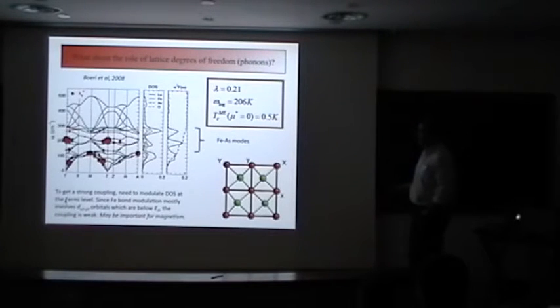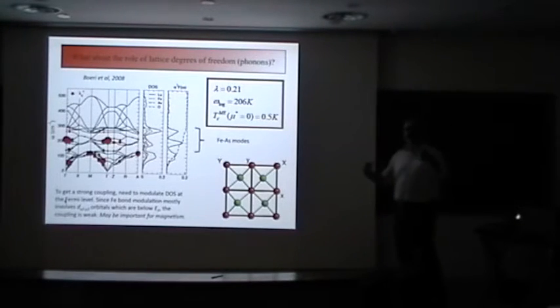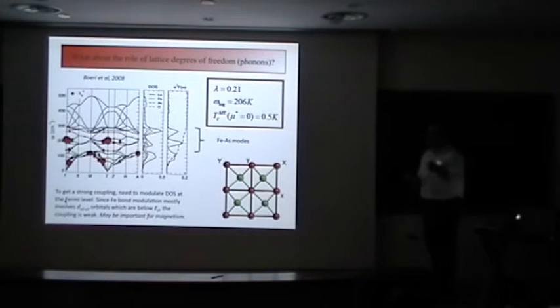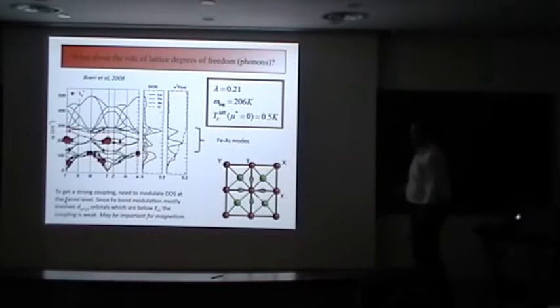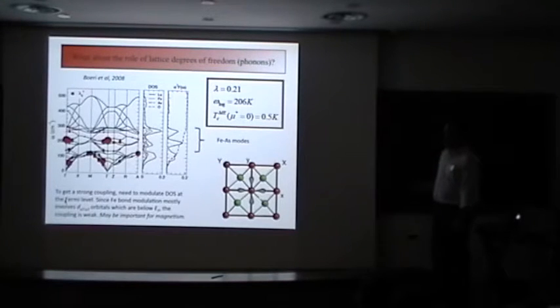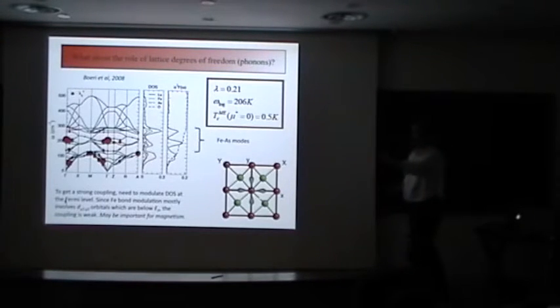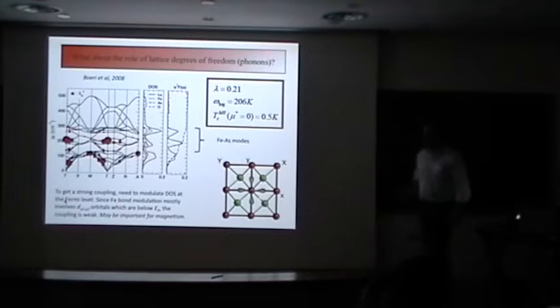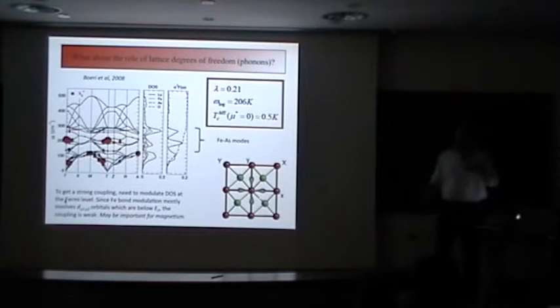The reason for that is pretty straightforward: if you want to gain energy from the electron-phonon interaction, you have to modulate a lot of the bonds connecting iron to iron or iron to arsenic. Looking at the iron-to-iron orbital that would be most sensitive, it's the x squared minus y squared one, which would be sensitive to this modulation. Because of the EGs being inverted, this orbital sits below the Fermi level. So anything connected to superconductivity near the Fermi surface would have a weaker coupling there. This may be important for magnetism, which extends over a larger energy region than superconductivity, but the point is it's not strong enough.